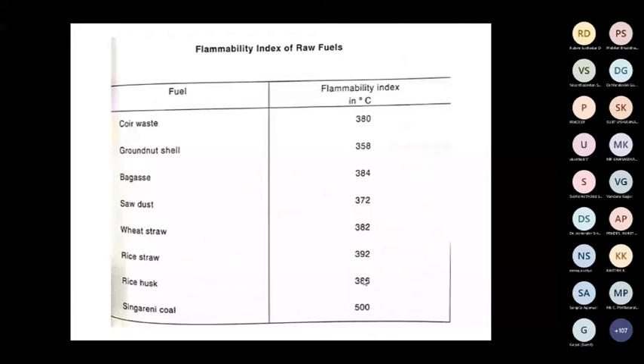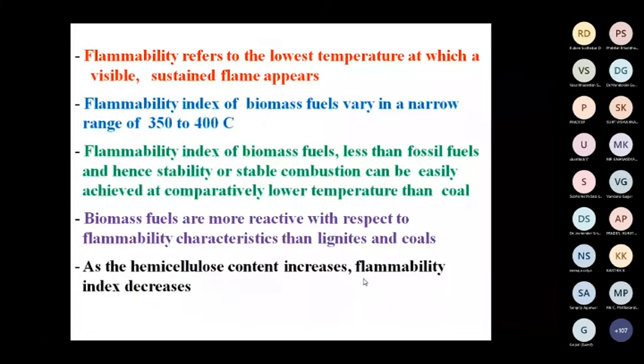So flammability refers to the lowest temperature at which a visible sustained flame appears. The flammability index of biomass fuel is in a very narrow range, 350 to 400 degrees C. The flammability index of biomass fuels is less than that of fossil fuels, and stable combustion can be easily achieved at comparatively lower temperature than coal. Biomass fuels are more reactive with respect to flammability characteristics than lignites or coal. As hemicellulose content increases, flammability index decreases. The higher the hemicellulose content, the more volatile. So naturally, the flammability index or temperature will come down. Easily ignitable.